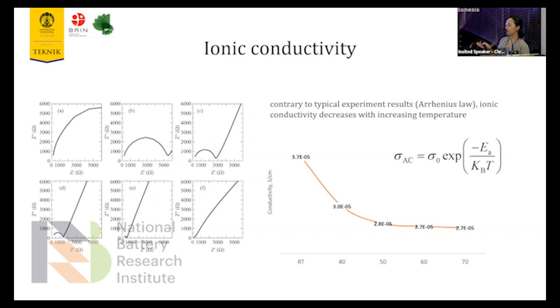And then this is the plot of the ionic conductivity when we elevate the temperature and calculate the impedance. We can see on the graph on the right that from room temperature, the ionic conductivity is 3.7 times 10 to the power of -5, and it decreases as we increase the temperature. And this at first confused us as to why, because it is in contrast to the typical Arrhenius law. We can see on the formula that usually ionic conductivity increases with the increasing temperature, but here in our experiment, we see that it is steadily decreasing.